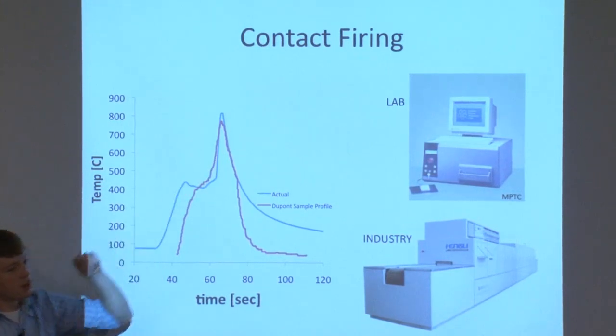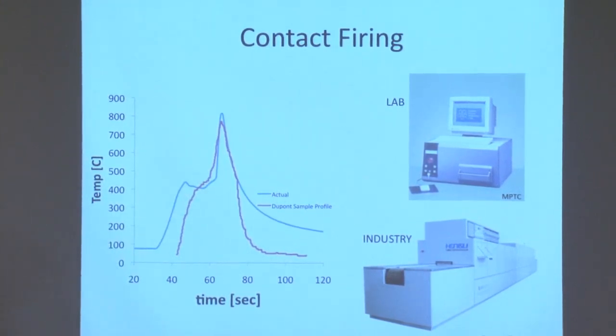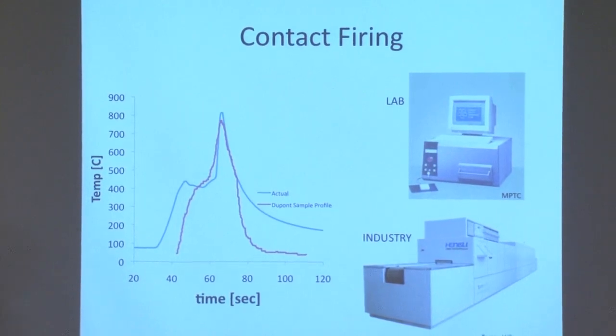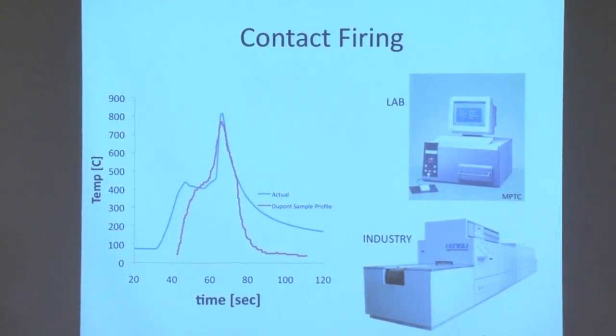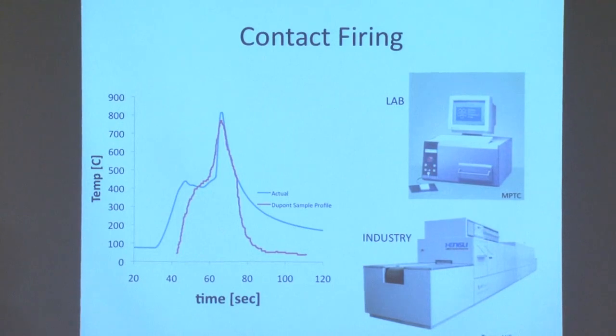That firing will, during that peak, also simultaneously, these metal particles will melt and form this triple eutectic point with the silicon underneath it. And so the triple comes from the silver, the silicon, and the lead. The lead actually dissociates from the glass. This lowers the melting temperature of that mixture. And you can make good ohmic contact with the surface.